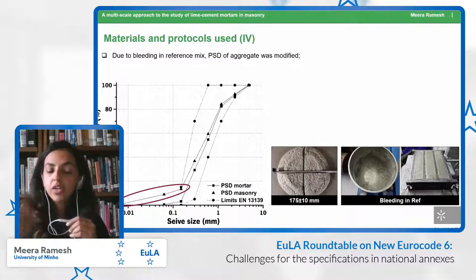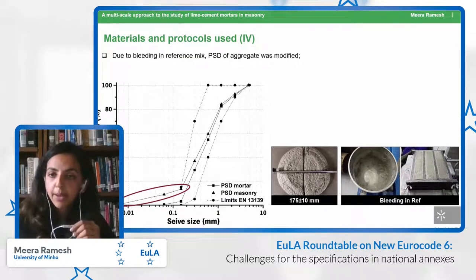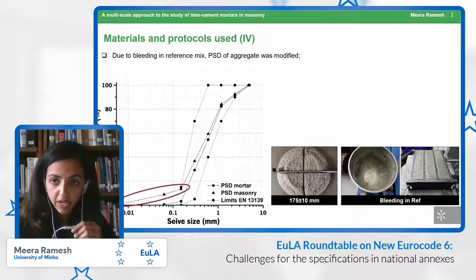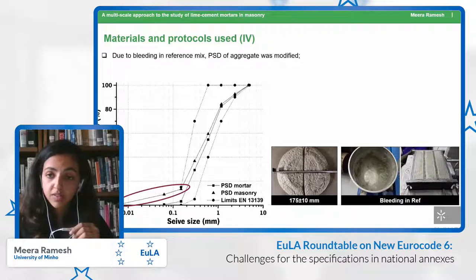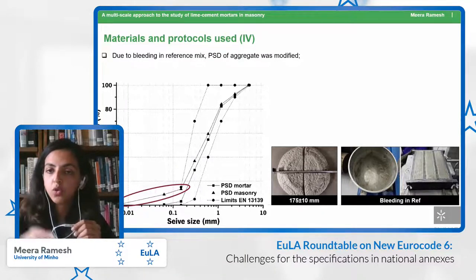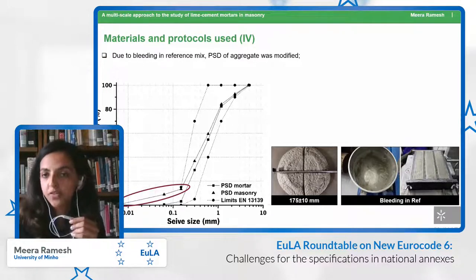So finally, we figured out that the problem perhaps was that in our aggregates, there were no particles of size less than 63 microns. And to test this hypothesis, we used the same binder, but a river sand from 0 to 4 millimeters, and it turned out to work. It worked out perfectly.